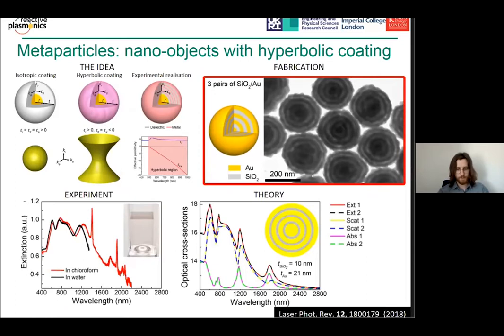So in addition to natural materials, we're also interested in fabricating metaparticles. So these are materials that aren't found in nature. And the idea behind these metaparticles, which have this kind of onion structure of alternating layers of gold and silica, is that if we put an anisotropic material on top of a plasmonic material, we can access this hyperbolic response, which will allow us to tune the plasma frequency and the dielectric permittivity, and therefore the wavelength at which we can operate over a larger range of wavelengths.